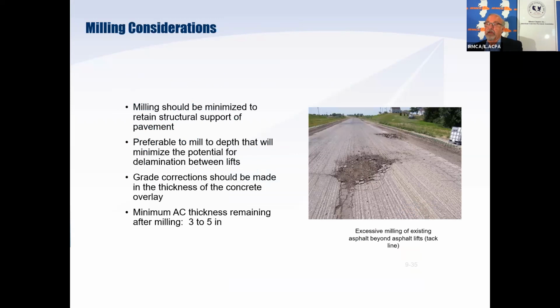So one thing to remember, and this is something that has come up several times in the last 6 months. If I mill my pavement, I'm expecting to do a bonded overlay. Well, I need to have somewhere between 3 and 5 inches of remaining asphalt after I mill the pavement. What you see in that photo is the milling operations went clear down to the subbase, which means I do not have adequate asphalt to bond to. Well, if I can't bond to the asphalt in order to transmit some of the load, then my overlay is not feasible. I'm going to have to go back to the drawing board.